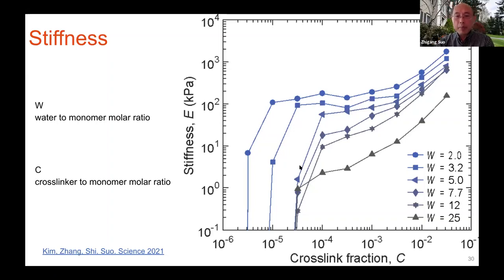So what we made is, essentially, here is a measurement of stiffness as a function of the concentration of crosslinks. If you have a high concentration of crosslinks, the material becomes stiff, right? You can see it becomes stiff, that's true. Normally, people make this gel with a C value, a ratio of the number of crosslinks to the number of monomers. So typically you have maybe 1,000 or 100 monomers per chain.